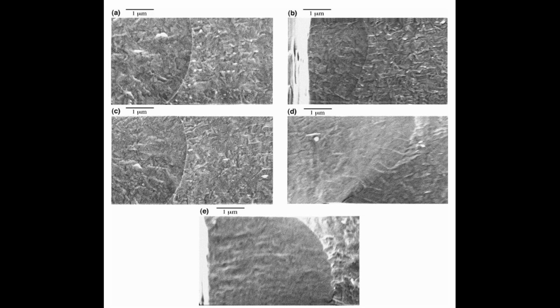Yeah. Any other factors? They also noted that the crack didn't always propagate in a perfectly straight line. There were sometimes small variations in the crack path direction. And they also speculated about that high-temperature annealing step, the 1,000-degree C bake. The one needed to remove stress. Exactly. While essential, they suggested it might have subtly different effects on the very tip of the crack depending on the local grain structure right there, maybe causing a tiny amount of crack tip blunting due to atomic rearrangements, like dislocation emission.